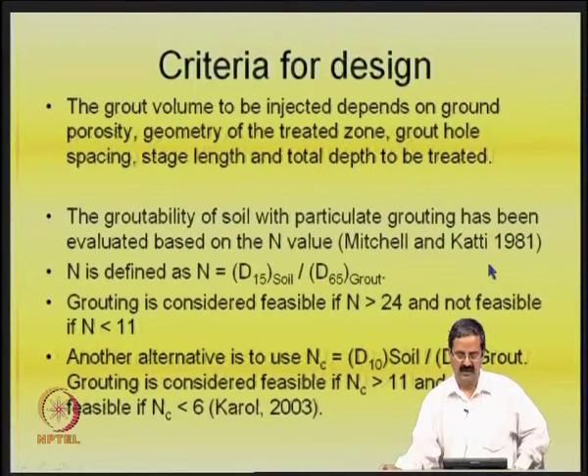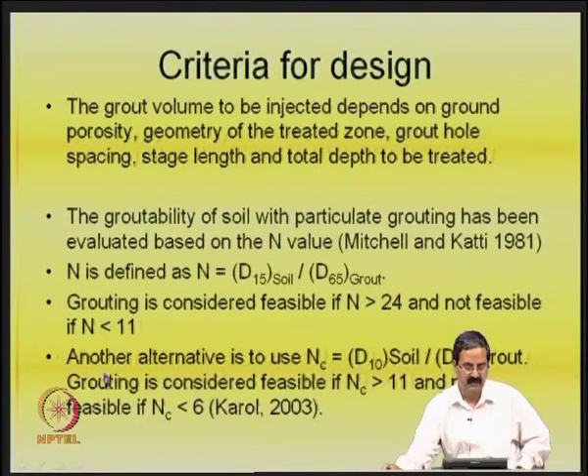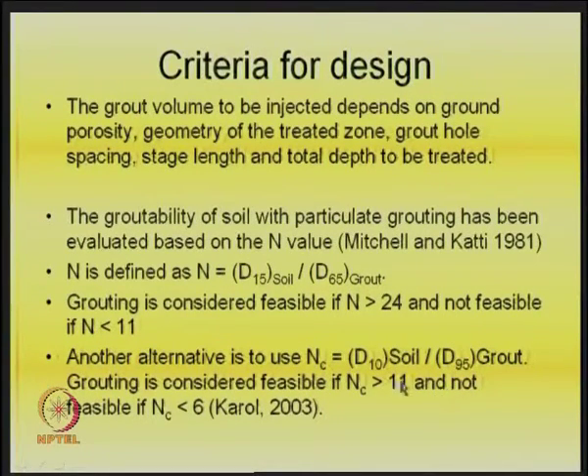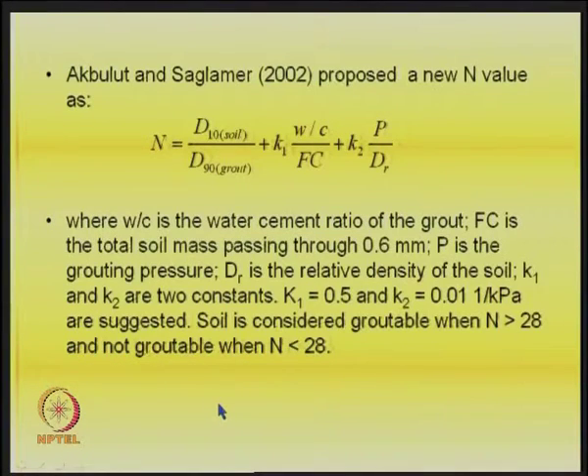Some people use another classification called Nc, comparing D10 of the soil with D95 of the grout — if Nc is greater than 11 it is acceptable, but less than 6 it is not. Researchers have been working on this, particularly for big projects like earth dams, where the foundation must be stable with no seepage, no bearing capacity failures. You need a proper understanding of pore size, grout size, and related information.